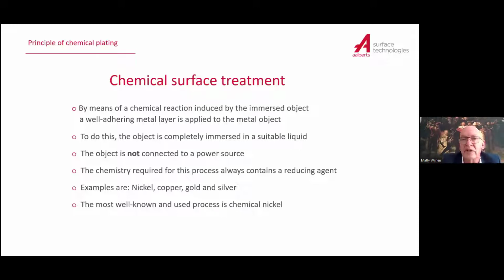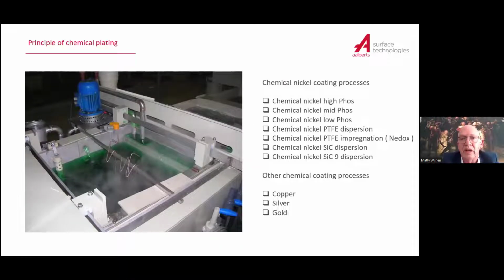And I think that most of the companies, most of the people who are listening, know this process. When you look at the chemical nickel bath, you see what I mean. You see there are bars enough, of course, but you don't see any anodes on the sides, and you don't see any connection for current in the middle of the tank. It's just a tank which has high temperature. You see the vapor evolving, but otherwise you don't need any current. That's the chemical nickel process.